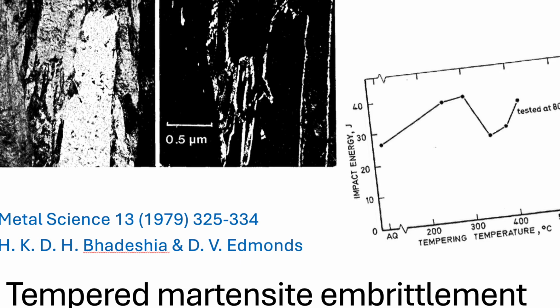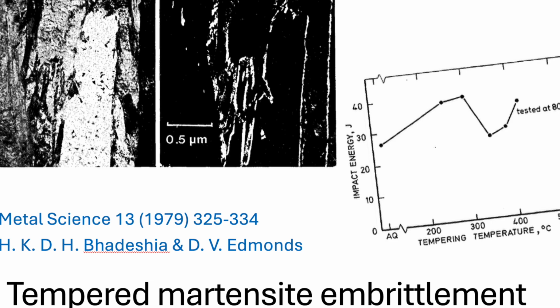So it's not a gradual decline, it's a sharp drop. Exactly. It's not a slow trend. It's a sudden, really sharp, localized nosedive in performance right in that window. And what makes that so surprising, I guess, is that the overall structure should be getting softer, maybe slightly tougher as you temper it higher. Right, precisely. And that's where you have to look at the contrast with hardness.